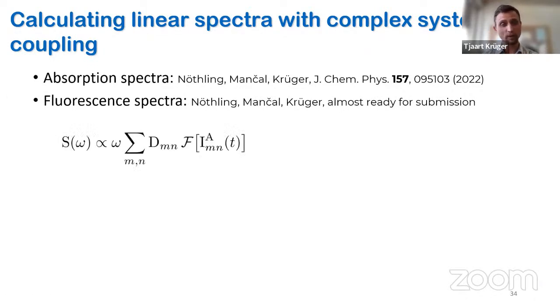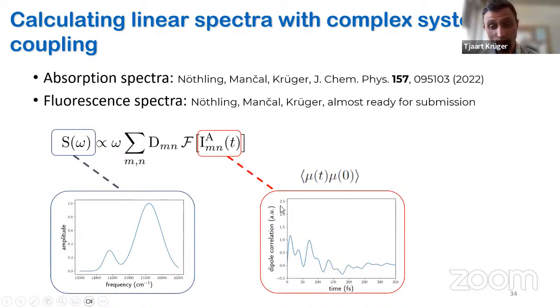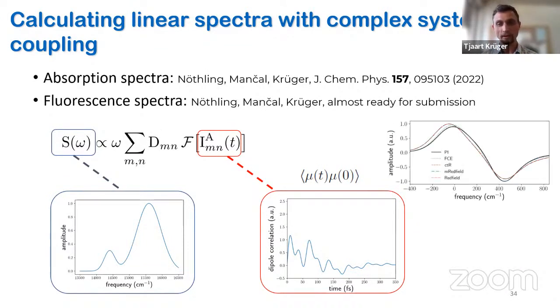And how this works, very briefly, is that one would like to calculate the linear spectrum as a function of frequency. Okay, and this is directly proportional, firstly, to the dipole correlation factor, which is the factor that is not trivial to calculate, because this includes the response of your molecular system to the incident electric field of your electromagnetic wave. Okay, and it also takes into account the electron-phonon coupling, dipole-dipole coupling, so all the interactions that are involved. One takes typically a Fourier transform of this, to get all the main frequencies that are involved in this dipole-dipole coupling factor. Okay, and this is the dipole factor matrix that specifies the type of spectrum that one would like to calculate. Okay, and from this one can calculate all the different types of spectra and compare the performance of different methods.